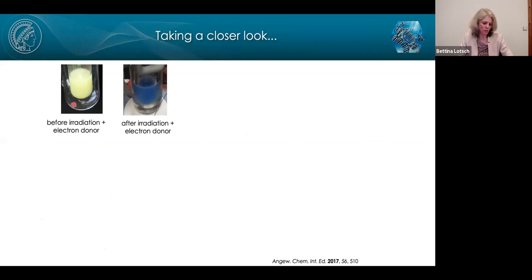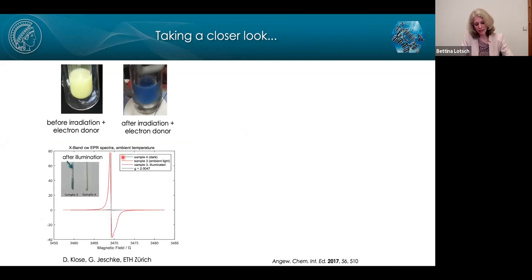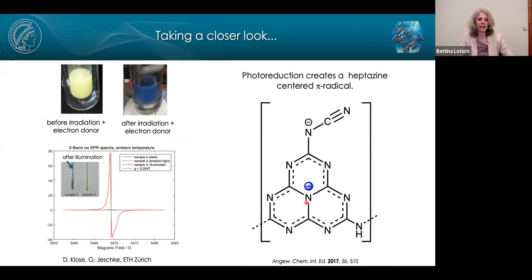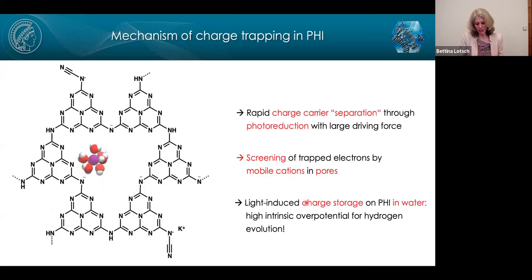Before irradiation and in the presence of an electron donor, and then we irradiate it, and then we see that the system turns blue, and it has a clear paramagnetic signature as seen by EPR, and this signature is consistent with a pi-centered heptazine or heptazinyl radical. Now, at this stage, let me briefly recapitulate and summarize what we've seen so far.